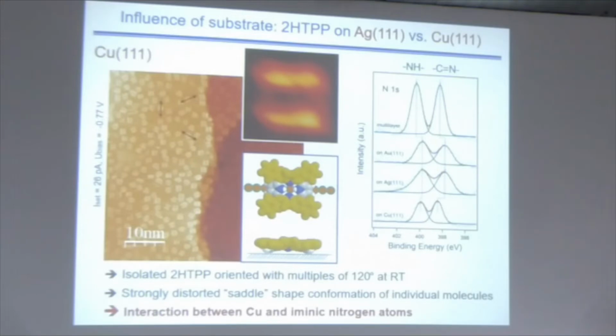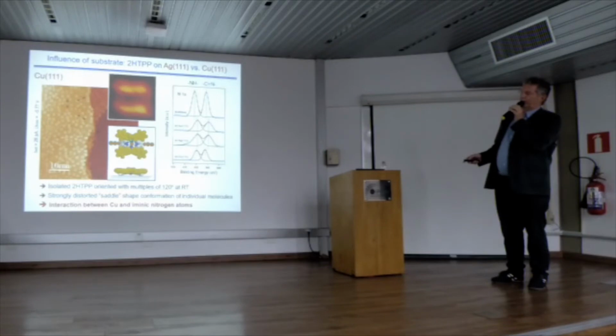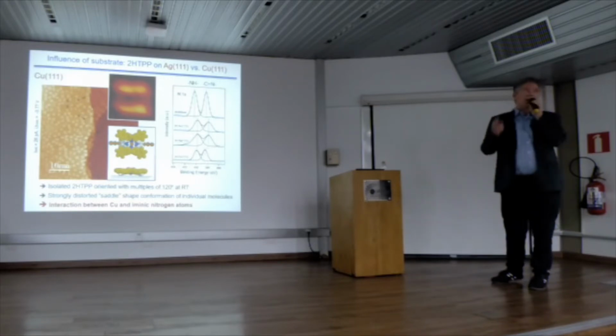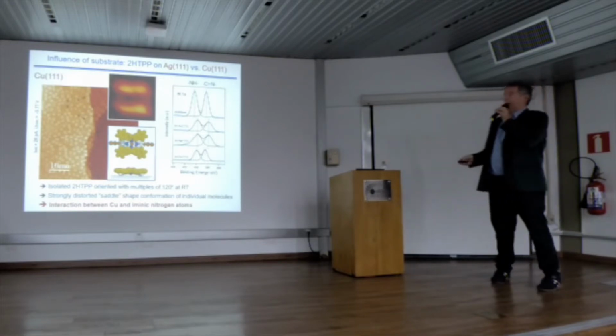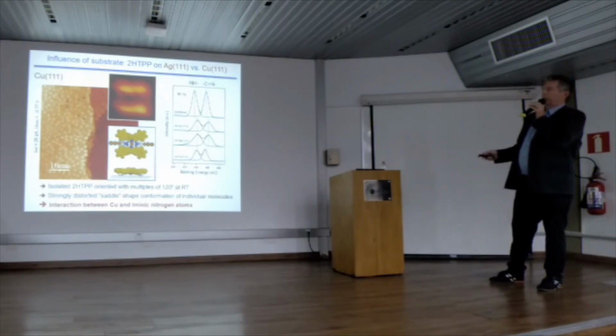This well-defined orientation, or this specific adsorption site, is also reflected in XPS. Let's start with a system that is very easy, namely this is multi-layers of porphyrins. So you only have porphyrins, no substrate, no nothing, and it's a free-base porphyrin. There's no metal atom in, and so you see you have these nitrogens without hydrogen, and this with hydrogen. I told you that before. 2 peaks. This is the chemical shift because they're bonded differently. The intensity is 1:1 because this is 2 and this is 2.